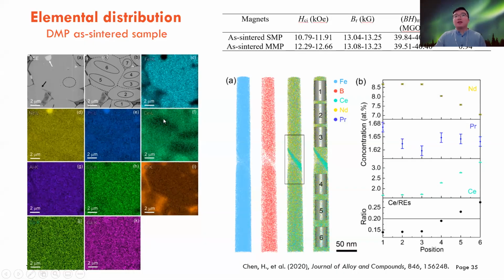We can see it's not like that typical core-shell, but a non-uniform distribution of the cerium in the matrix phase here. And when we use atom probe tomography, we can know that beside this grain boundary, you can see 1, 2, 3, 4, 5, 6, that's in 2 different neighboring grains. For the 1, 2, 3, the cerium actually remains at a low constant. But for the bottom here, we can see an enhancement of the cerium concentration, which is led by these dual main phase techniques. Sorry, I forgot to mention, the point of this work is that we found the coercivity of this dual main phase, multi-main phase magnet is actually higher than the single main phase one here, even with little sacrifice of the remanence and the BH maximum magnetic energy.